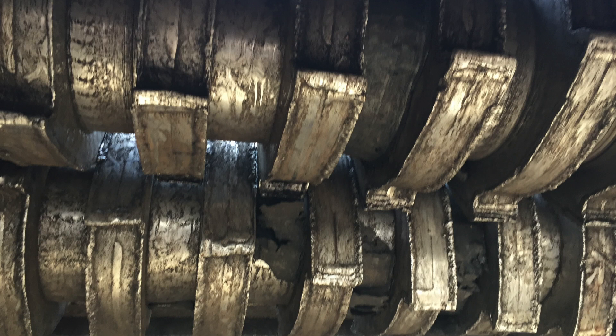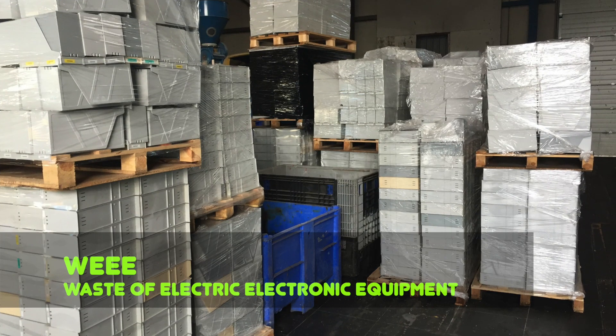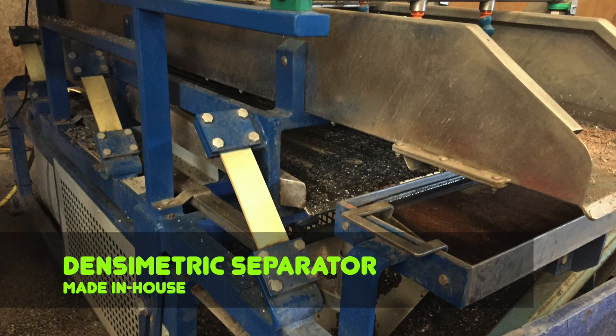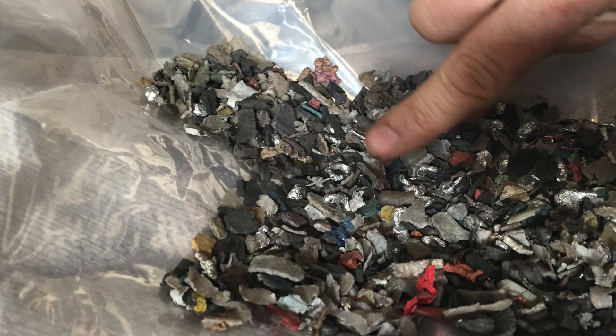Part of the highly pure raw materials is re-granulated on an old Erema, but not more than 20–30 tons per month. There is also some WEEE — waste of electric and electronic equipment. It is crushed on the same two-shaft shredder, additionally crushed on a granulator, and then separated on a densimetric separator of their own manufacture, where plastic is separated from non-ferrous metals.